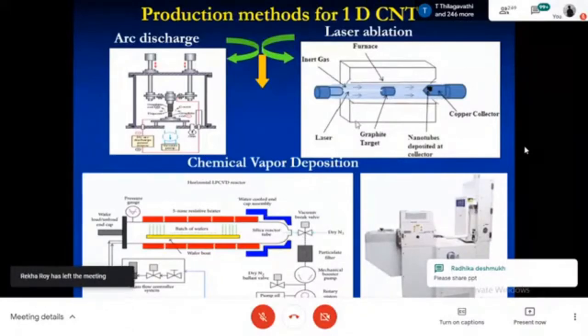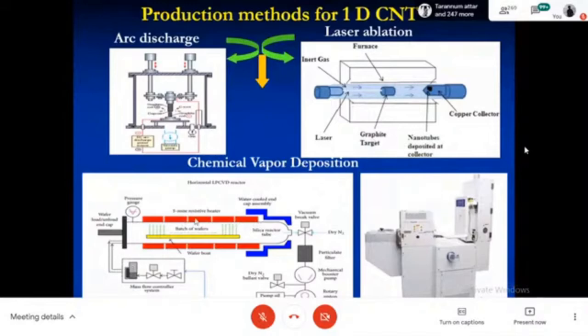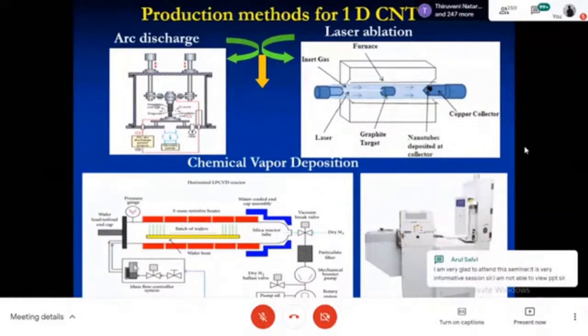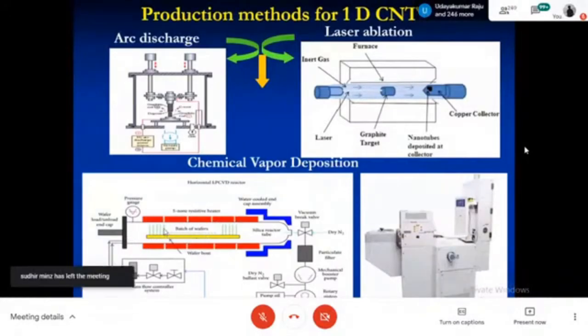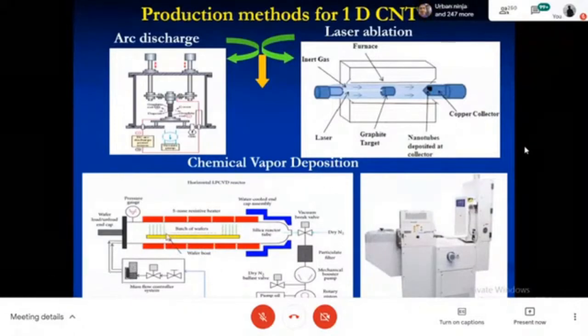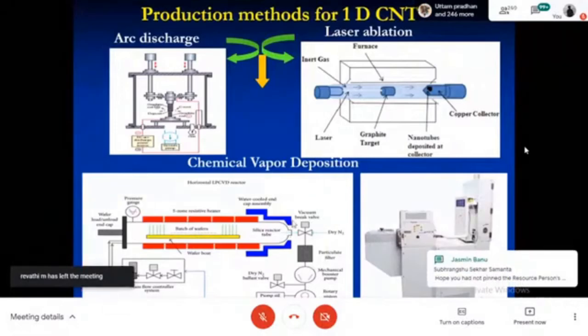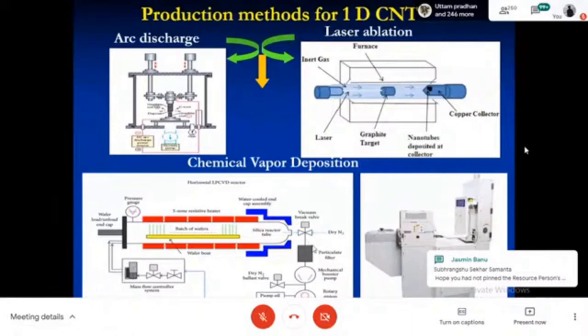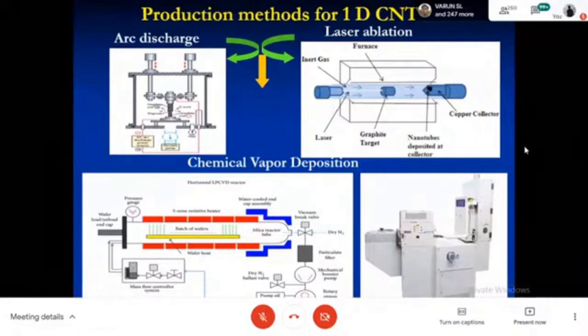And so the improved version of this laser ablation is the CVD process, where we control the temperature along the length of this reactor, because this is actually a 5-zone resistive heating furnace. Then you have the carbon source coming here, and this is the substrate. And you can have any kind of substrate depending upon the operating temperature of the reactor. Then you have the one-dimensional nanostructures grown from the surface using the source which is coming from the other side. Of course, there are some peripheral devices attached to this to control the temperature, vacuum, and other things. And this is the typical CVD reactor. And this is the most optimized technique now.